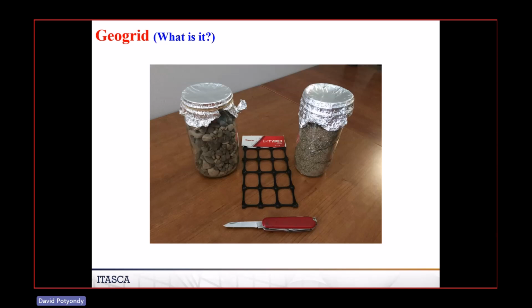The ballast is hopefully stiff because the asphalt, when it flexes, the more it flexes, it eventually starts little fatigue cracks to grow out of the surface. Those fatigue cracks are bad because water gets in and it's a feedback mechanism, and then eventually your road starts to crack. So what you want is that ballast material, ideally, to be infinitely stiff. To make it stiffer, what they have found is they put a layer of ballast and then they roll this stuff on there. And then they put more ballast.